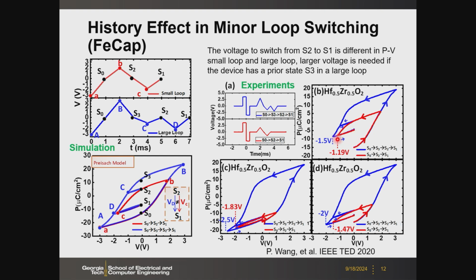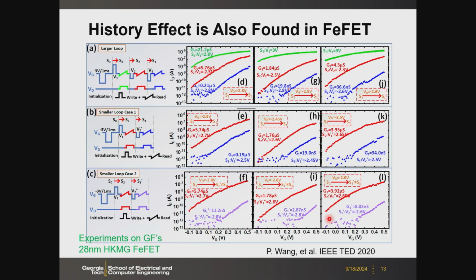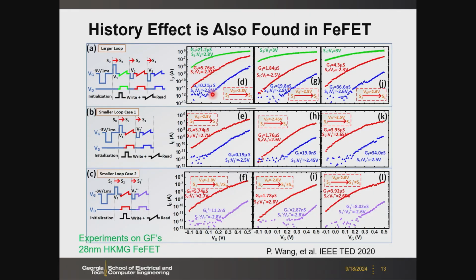So here the switching voltage is different. And then we also verified this from the FeFET. As I said earlier, we have access to GlobalFoundries 28 nanometer FeFET wafers in our lab. We tested similar larger loops and smaller loops in the FeFET. Here I won't go into the details of those graphs, but I just want to draw your attention to, let's say, 2 examples. Because for the FeFET, we read out the drain current as a mechanism to determine the intermediate states. So here, for example, in this larger loop, in order for us to switch from S2 to S1 state, let's say the ID-VG curve, right?